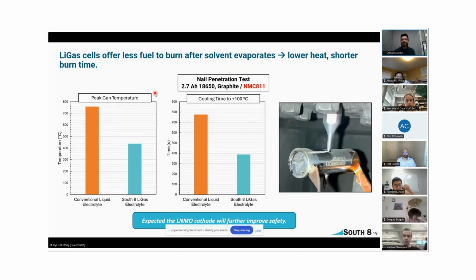So here's a quick test: a 2.7 amp hour, 18650 graphite anode NMC cathode, nail penetration, where we compared two jelly rolls, one with liquid electrolyte, one with South 8's liquefied gas electrolyte. When we drive this nail through the can, we can see the peak temperature of the liquid electrolyte hit 700 to 800 degrees Celsius, whereas the South 8 cell was considerably cooler, right around 400 degrees Celsius.